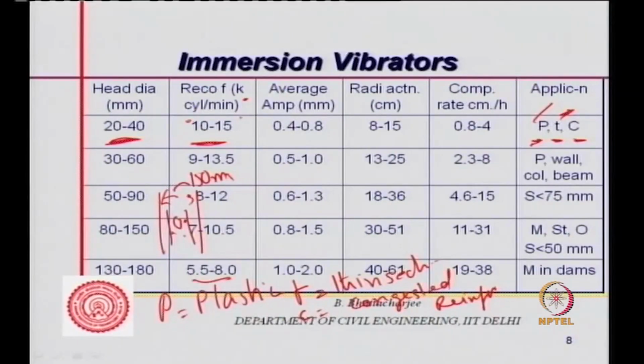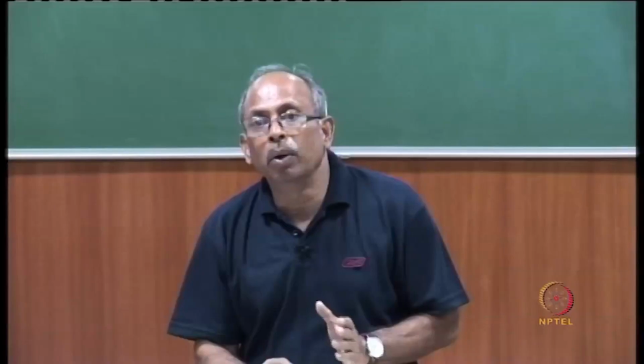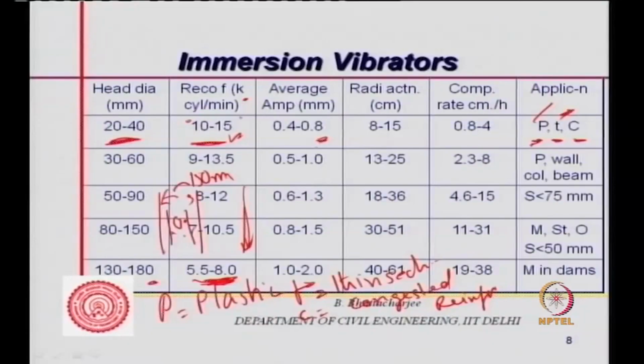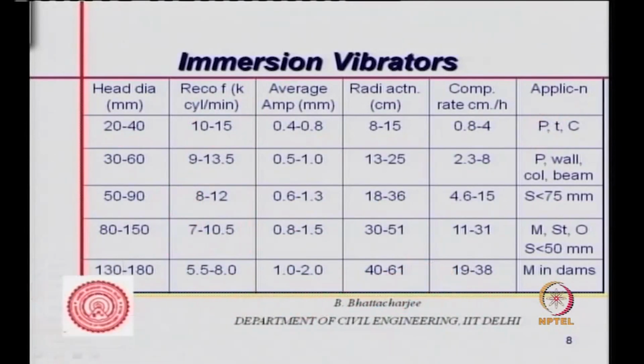You can see as this diameter increases, frequency reduces. So this is high frequency, this is lower frequency, all right. Average amplitude is low here, average amplitude is high here. So when average amplitude is high, frequency will be low. When average amplitude is low, frequency is generally higher. The radius of action is 8 to 15 centimeter. In this one, the radius of action is much more. So where you have a thin section, plastic concrete, congested reinforcement, you might use this.